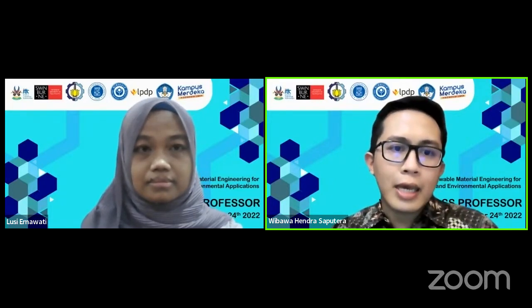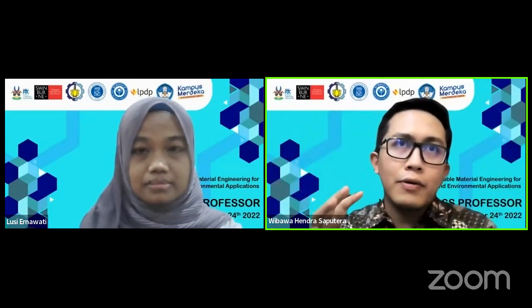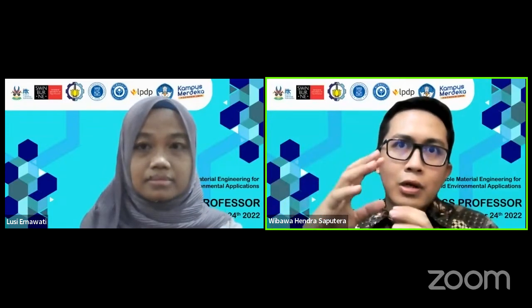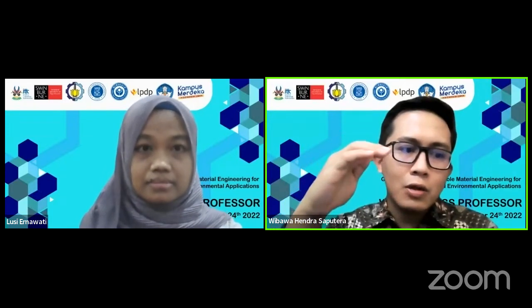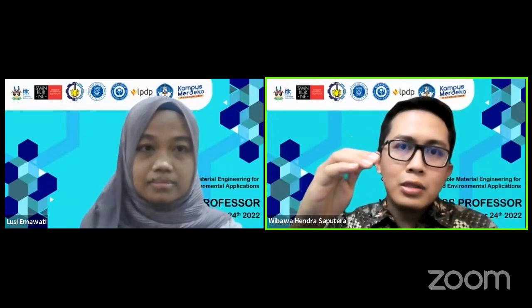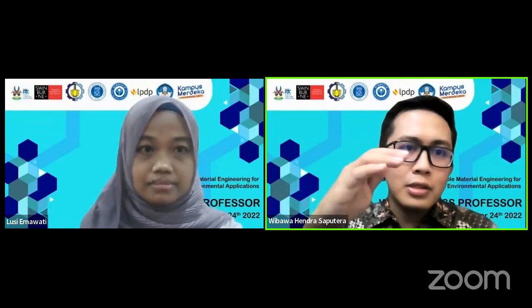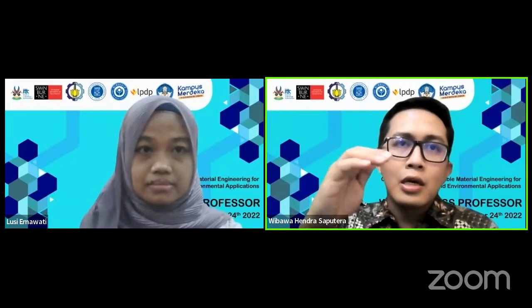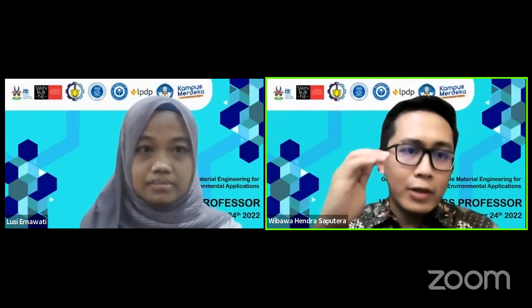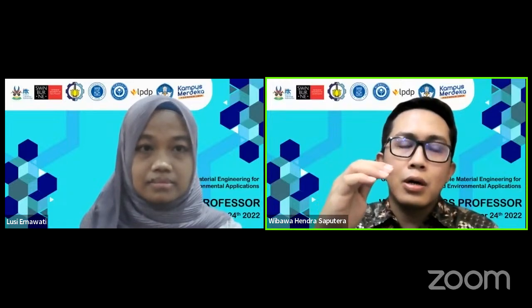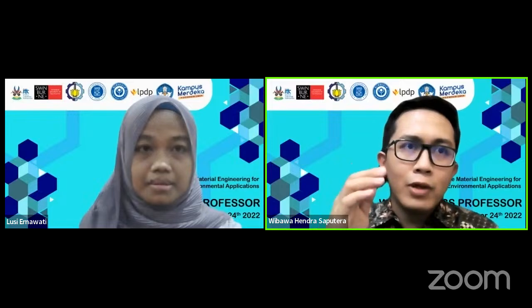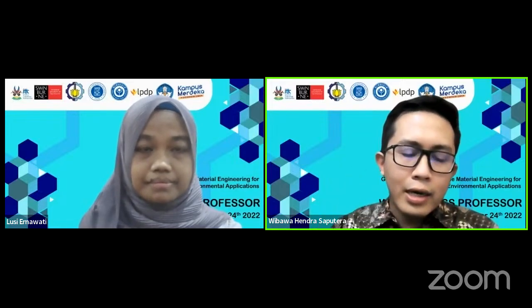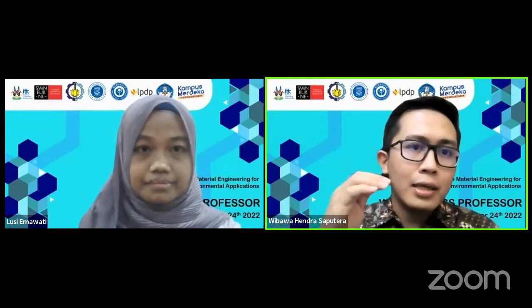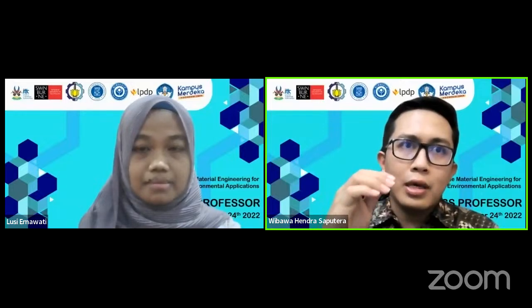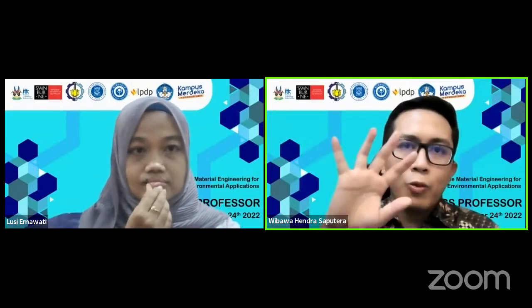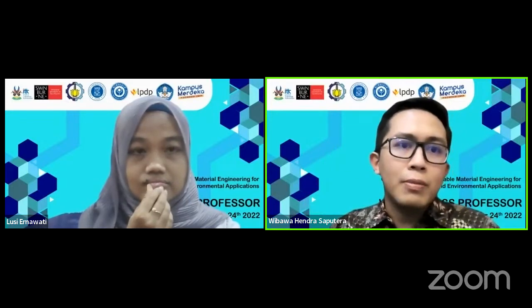effectively provide interactions between the catalyst and hydrogen. Because as we know, in the photocatalytic decarboxylation process, when the electron is separated from the hole, the negatively charged separated from the positively charged, the electrons reduce the hydrogen into hydrogen atoms, which creates a hydrogen-rich surface on the catalyst. While on the valence band, the positively charged hole can react with the fatty acid. So the fatty acid will get oxidized and will remove CO2 to form what we call the alkyl radical. This alkyl radical and the hydrogen-rich surface on the catalyst will react to form the hydrocarbons, or the alkane.